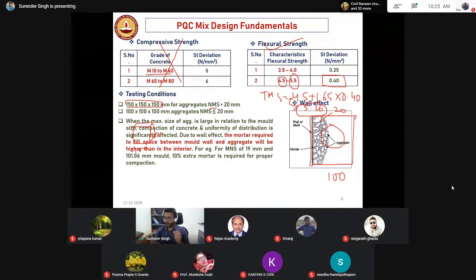We know cement is the costliest component, right? You are sitting in the lab, and because you do not have a 150 mm specimen mold, you are taking a 100 mm mold and then compacting it. 10% extra cement paste is required, and then you will get the strength. But in the field, that 10% extra cement means the economy of the project will be significantly lower; your cost will be significantly rising. So if your nominal maximum size is less than 20, then only you can go with a 100 by 100 by 100 mm cubical specimen. If your nominal maximum size is more than 20 mm, to avoid the wall effect we have to cast cubical specimens of 150 by 150 by 150 mm.